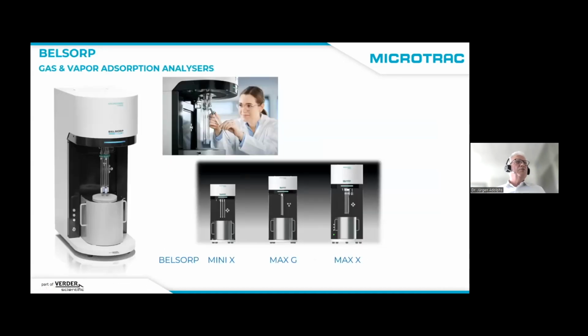So the equipment we use is shown here for applications for very fast surface area measurements. We can do this meanwhile in the range of about 20 minutes for 4 samples, for example, using the BELSORP Mini X. It's equipped with a rotary vacuum pump, while the systems Max G and Max X use much better vacuum. They are equipped with turbomolecular pumps and also dedicated pressure transducers working in the pressure range down to 0.1 torr, for example, where we can then also determine the micropores.